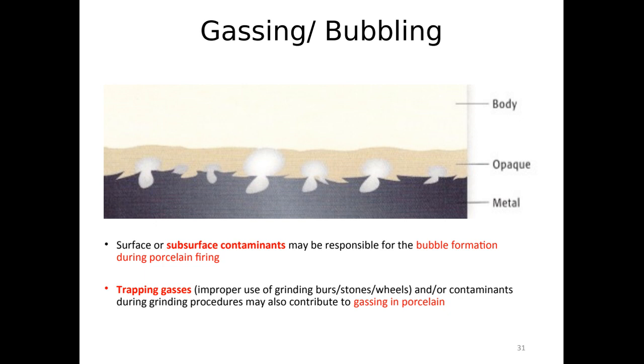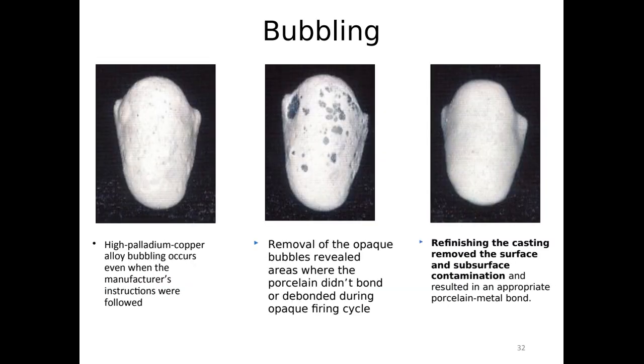Gassing or bubbling. Surface contaminants may be responsible for the bubble formation during the porcelain firing. So if we didn't clean and, so to speak, disinfect the coping before receiving the porcelain, we may have a cross-contamination or surface contamination that can interfere with the bonding between porcelain and alloy. Trapping gases, improper use of grinding burs, stones, wheels, and contaminants during the grinding procedures may also contribute to gassing in porcelains. Bubbling.